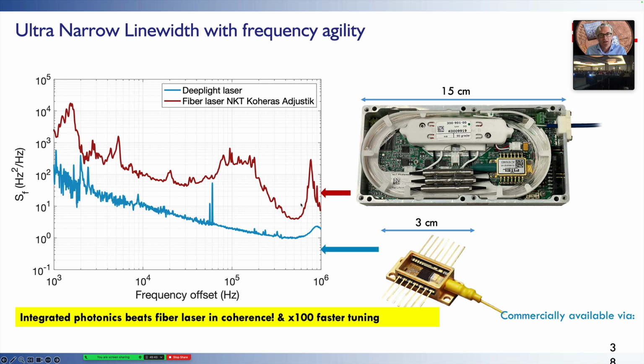We were very surprised that due to this very high quality factor, the integrated silicon nitride self-injection locked lasers can operate well below the phase noise of a state-of-the-art fiber laser as used for fiber sensing. So this provides an opportunity for the first time to create integrated photonics lasers that are not only compact, but most importantly, their performance challenges conventional legacy lasers. This is due to the use of this very low loss circuitry based on silicon nitride. We have commercialized this technology with the company Deep Light, founded 3 years ago.